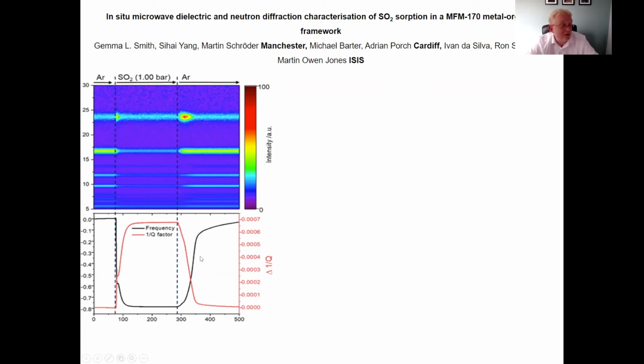And that means we can use this simple dielectric resonator as a way of measuring the amount of SO2 that's been sequestered within our gas filter. So if you imagine you're building a carbon dioxide or an SO2 filter to put on a gas stream, say from a power station or industrial process, you might want to know when that filter is full. You probably don't have the ability to take a sample of that to a neutron beam line every time you want to know if it's full, but you do have the ability to take a dielectric measurement. A resonator here might cost a few pence to build and measure, and so it becomes a very good method for diagnosing materials.